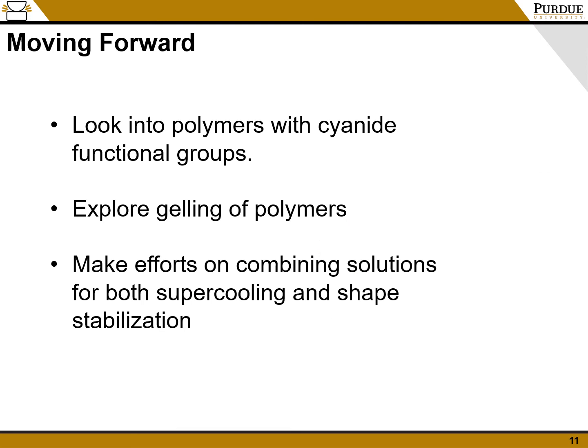So my recommendation after consolidating all of this information is to perhaps look into polymers with cyanide functional groups. This offers a solution to the supercooling without adding a nucleation agent because of the interaction of the salt ions with that cyanide functional group. In addition, look into the gelling of polymers to increase the viscosity of the PCM. By increasing the viscosity, you can reduce the leakage as well as how much the salt will precipitate out of the solution, effectively increasing the number of thermal cycles experienced by the PCM.